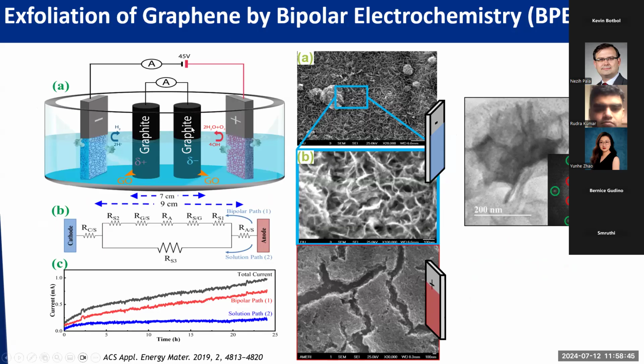We break the graphite into 2 pieces, and we connect the 2 pieces of graphite, those are bipolar electrodes, with a current meter. We can monitor the total current, the bipolar current, and the solution current, so we can even try to understand the mechanism. Another thing we found, by looking carefully at the negative feeding electrode, is that we actually have vertically aligned graphene deposited on the negative feeding electrode.